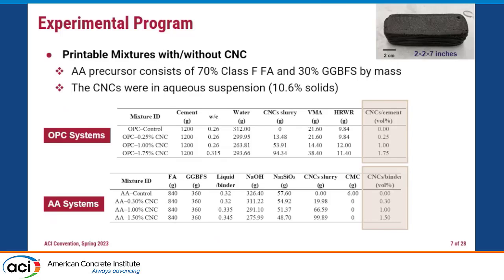So based on those criteria, we developed these 8 different mixes. In the top table, you can see the OPC mixes, the control without CNC and then different percentages of CNC by volume of the cementitious material. At the bottom, you see the alkali activated system, again the control and different CNC proportions. In the case of the alkali activated binder, we use a mix of fly ash, class F fly ash, and slag: 70% fly ash and 30% slag. Again, I'm going to discuss how we came up with that number. The CNC were in aqueous suspension at around 11% solids, and for the activator, we use a combination of sodium hydroxide and sodium silicate.